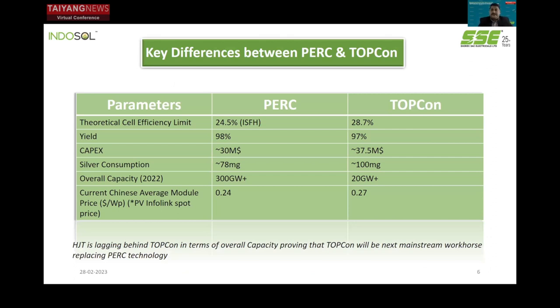This table summarizes the key differences between PERC and TopCon. While there is great potential and room for further improvements in cost (dollar per watt peak), efficiency in watts per watt is actually dictating the whole market scenario. Silver consumption is slightly higher for TopCon, but we are seeing a similar situation to what PERC showed four or five years ago, and it has since come down. TopCon has already over 20 gigawatts plus of installed capacity, and several hundreds of gigawatts are being planned in the coming years.